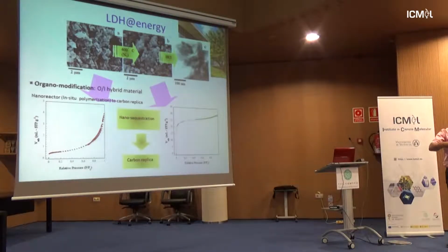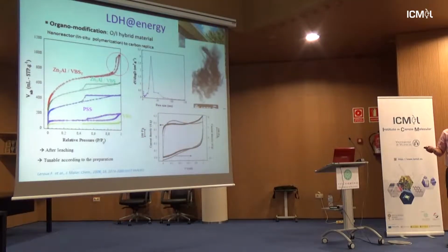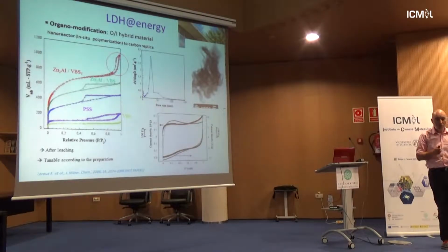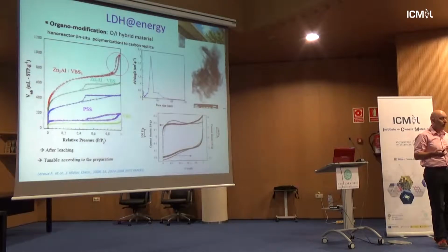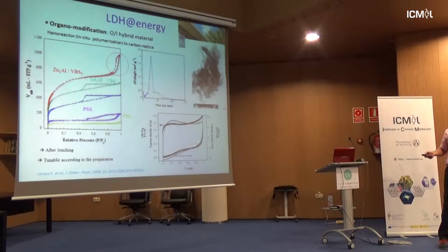Then you acid leach the small inorganic particles coming from the breakdown of the LDH, and you get rid of them, and they act as a pore-forming agent. And when you do so, you end up with a very large surface area, keeping the microporous surface as well as the mesoporous activity, because you get rid of all the inorganic part. So you get a dual micro-mesoporous carbon, so it can be of interest for all the supercapacitor applications in terms of energy.